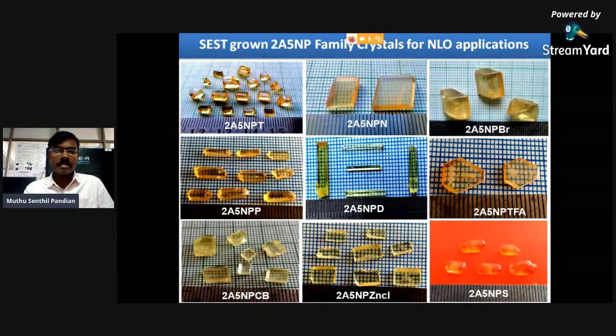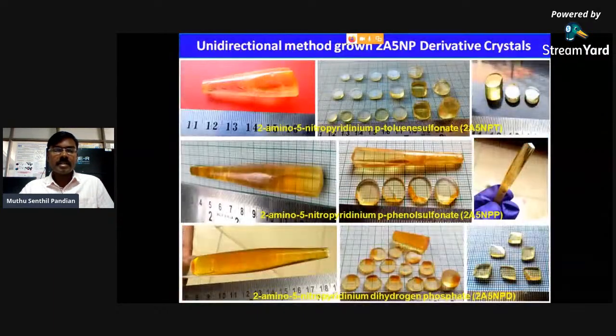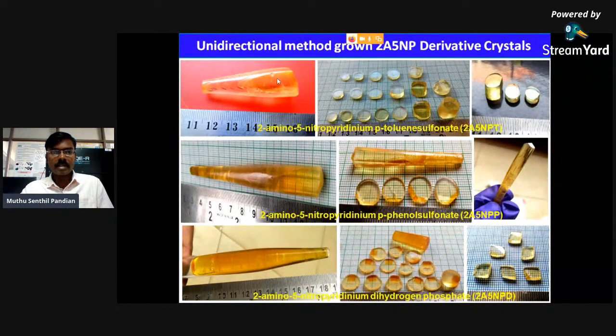For practical device application, we cannot use the conventional method grown crystal as it is. So in order to avoid this problem, we have developed this SR method, the unidirectional Sankaranarayanan-Ramasamy method. So this is the SR method grown 2-amino-5-nitropyridinium p-toluenesulfonate single crystals for practical device application. This is the crystal grown by SR method. This is the cut and polished wafers, and this is the SHG oriented, the same crystals.